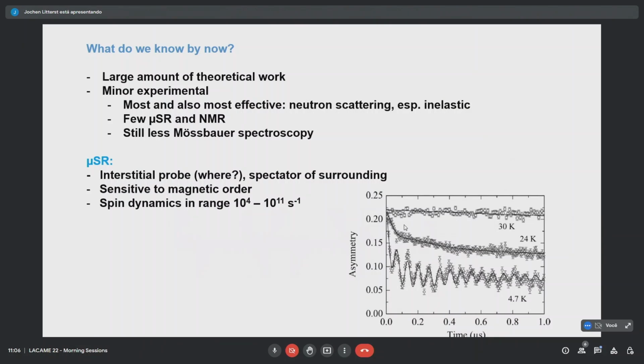So to summarize, what do we know by now? There's a huge amount of theoretical work, you can imagine, speculating what may happen. Minor experimental, most effective, I must say, is neutron scattering, especially inelastic scattering. There you can look for these typical liquid-like excitations. There are few muon spin rotation and also NMR experiments, NMR on copper, for instance. Still less Mössbauer, nearly no Mössbauer spectroscopy. So I wanted to look and see what we can see at all.